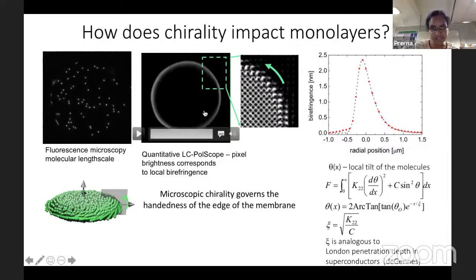You can take an intensity cut on this image to figure out what is called the twist penetration depth. So essentially intensity is low here, high here, and low again. And the way it decays from being high to low into the membrane gives you what is called twist penetration depth. And it's analogous to the London penetration depth. So there is a one-to-one analogy between how a smectic phase expels chirality and how a superconductor expels magnetic field. And so this analogy was first elaborated by de Gennes, for which he won the Nobel Prize as well.